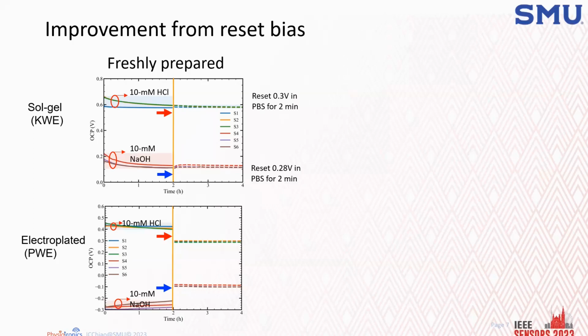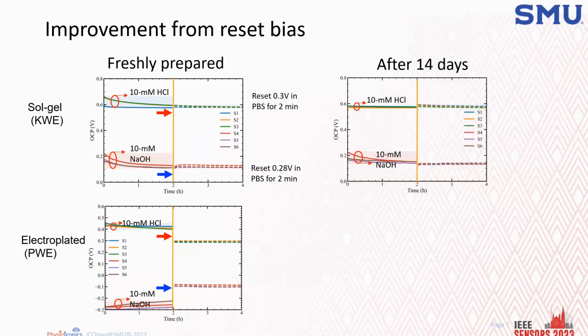And for electroplated one, the phenomena is also the same, that we found originally they had drift, and when we apply a voltage, after 2 hours, the drift disappeared. We also find something very interesting, that after 4 hours experiment, we wash them, dry them, put them away. After 14 days, we test them again.